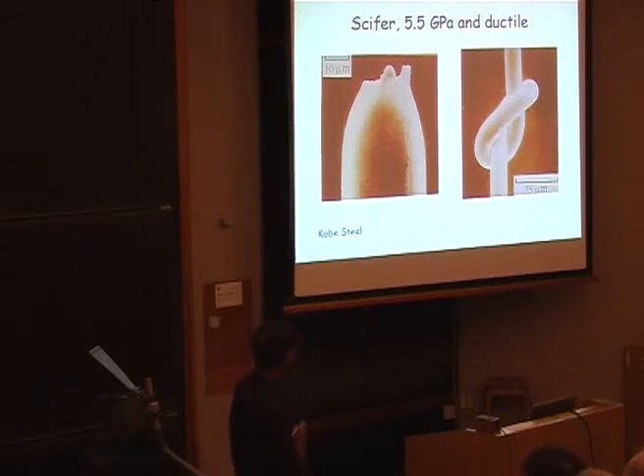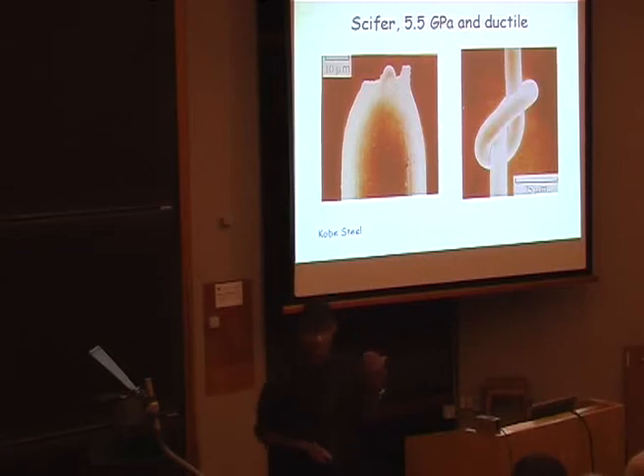And you can see that it's a lot more ductile than carbon fiber. And this is made by taking, let's say, 50 grams of iron and stretching it out into 2 kilometers. So it's very, very severe deformation, a true strain of 9. And here, unlike the previous slide, the strength is coming from the defects that we put into the material, severe defects. And the scale is reduced to about 5 nanometers when you look at the structure inside this wire.